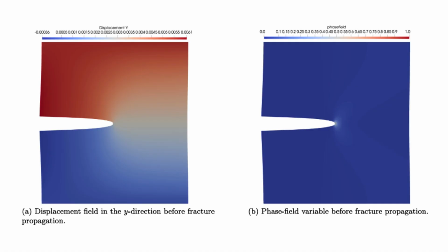It really is. You have a beam supported at the ends, maybe with a notch on the bottom, and you push down in the middle. Right. So you get tension on the bottom where the notch is, but compression on the top surface and near the supports. Loads of compression. So this test directly challenges that hybrid model. Will it correctly propagate the crack only from the notch tip upwards in the tensile zone, or will it incorrectly form cracks in the compression zones?